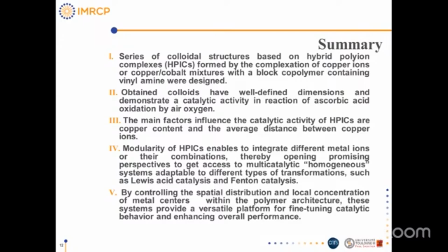So, a series of colloidal structures based on hybrid polyion complexes, HPICs, formed by the complexation of copper ions or copper-cobalt mixtures with a block copolymer containing vinylamine were designed. Obtained colloids have well-defined dimensions and demonstrate a catalytic activity in reaction of ascorbic acid oxidation by air oxygen. The main factors influencing the catalytic activity of HPICs are copper content and the average distance between copper ions.